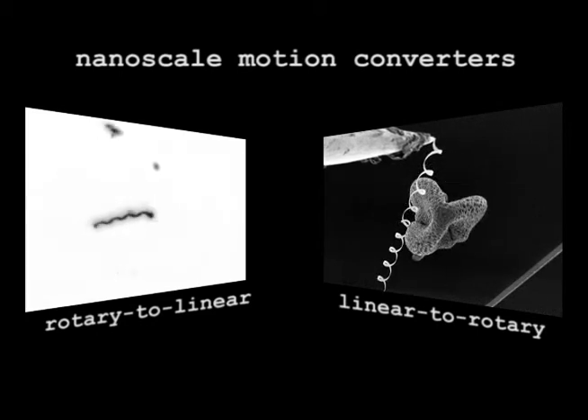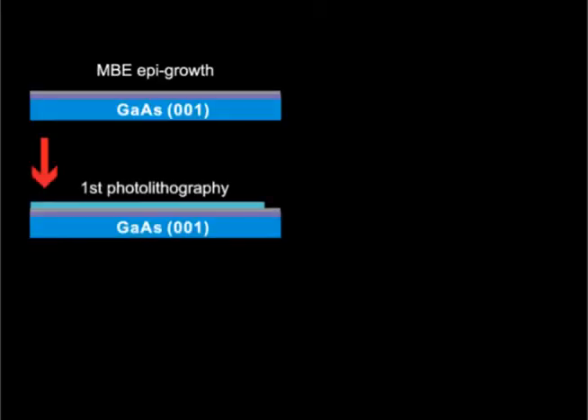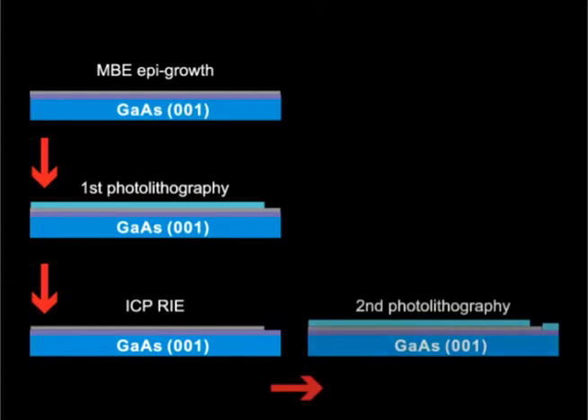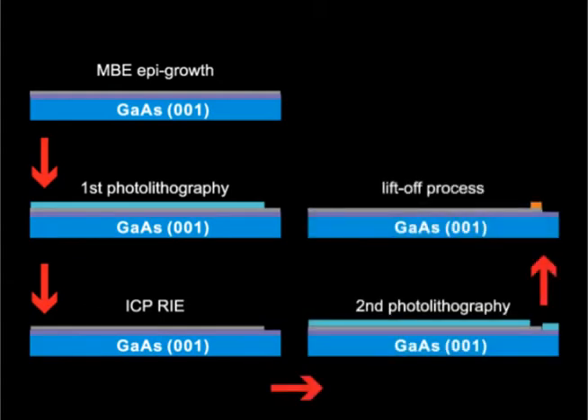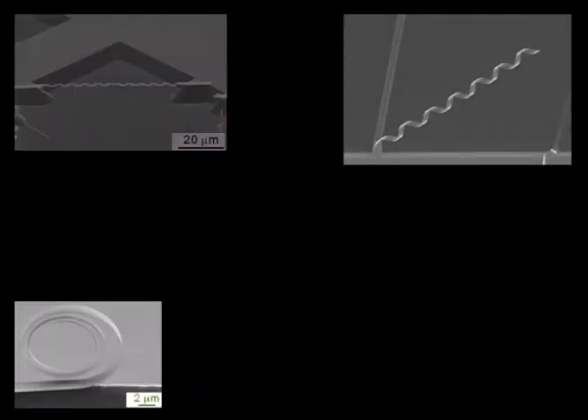The fabrication is based on the rolling of strained thin films. Coils with thicknesses of 20 nanometers and diameters on the order of 1 micron can be formed with pitches in the range of 10 to 50 degrees. Based on pattern designs, nanostructures have been fabricated such as tubes, coils, rings and spirals.